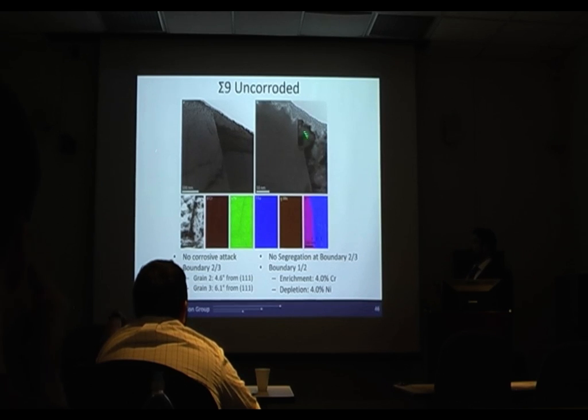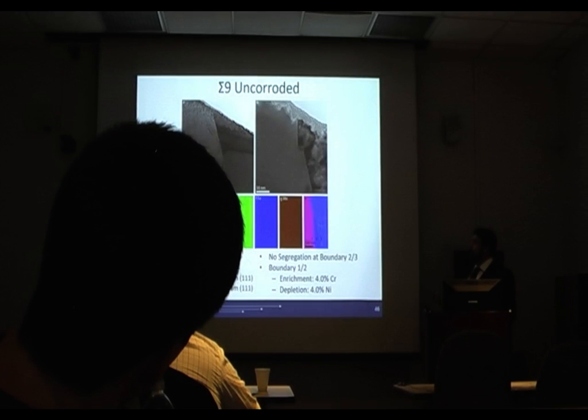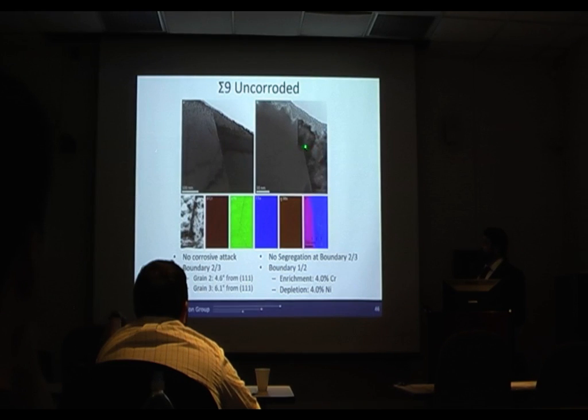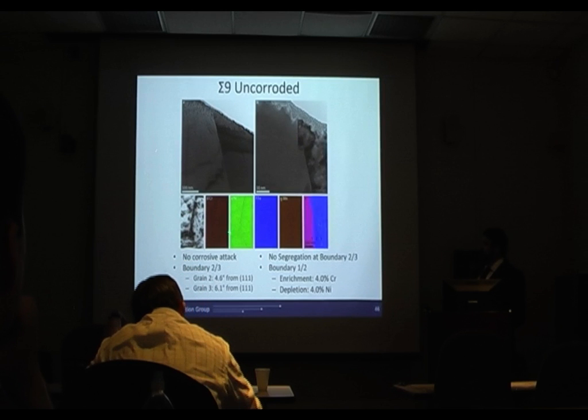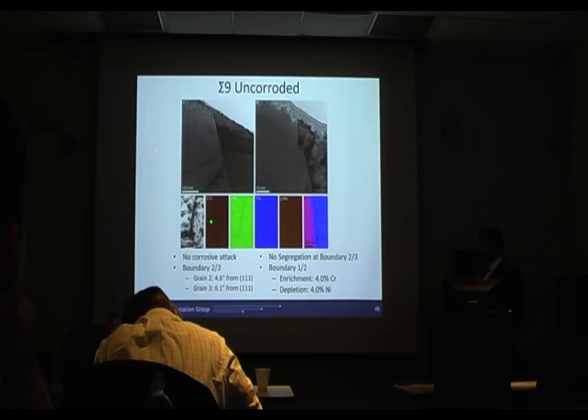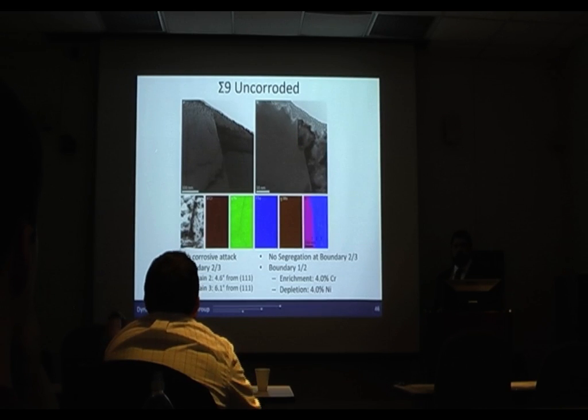So we have a coherent sigma 3 that we determined terminates within around 5 degrees of a 111, and then we have an incoherent sigma 3 where we have enrichment of about 4% chromium and 4% nickel. This is a sigma 3 misorientation, but we don't have the grain boundary plane for that segment.